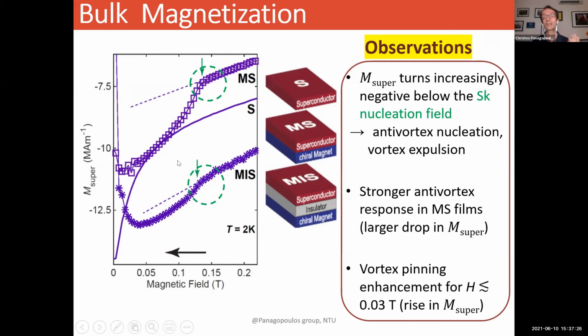What you observe immediately is three points. First, the superconducting component of the magnetization in our heterostructure turns increasingly negative below the skyrmion nucleation field, shown here in the green circle. And that indicates the formation of anti-vortices and vortex expulsion. Also, there is a stronger anti-vortex response in the MS films compared to the MIS films. There is a larger drop in the magnetization of the superconducting component. And finally, there is vortex pinning enhancement at very low magnetic fields, as you can see here.